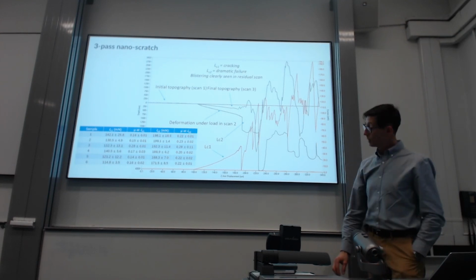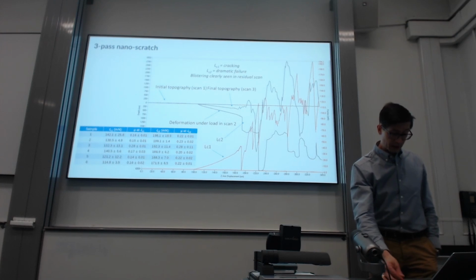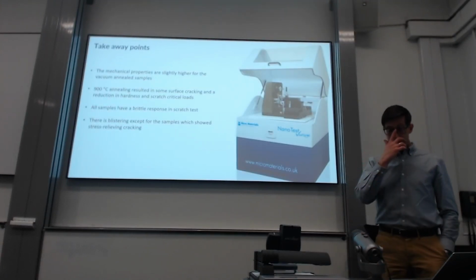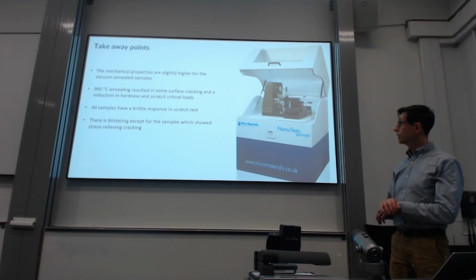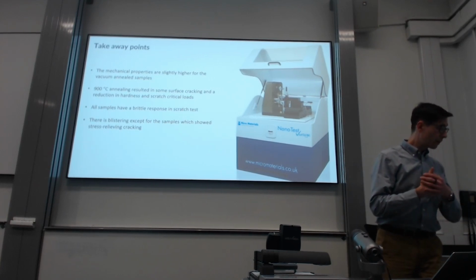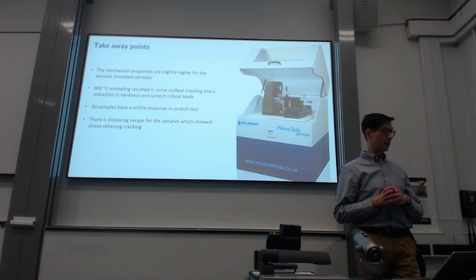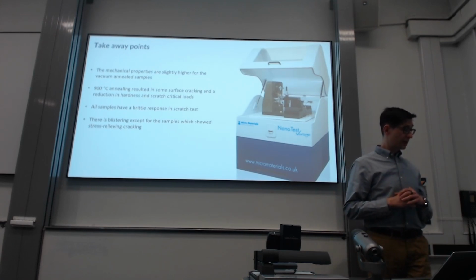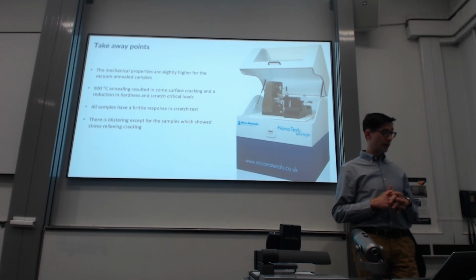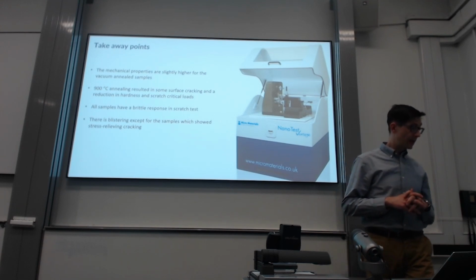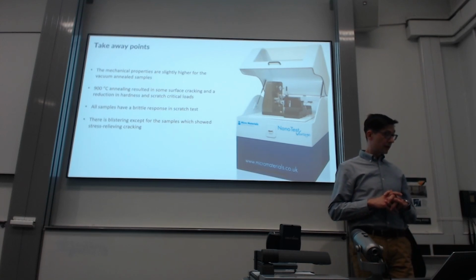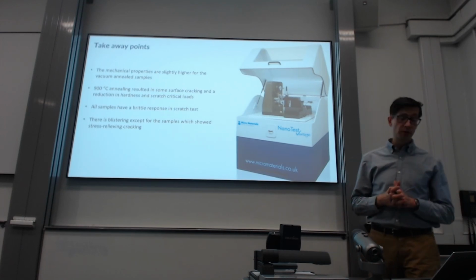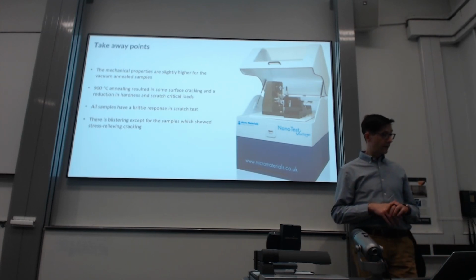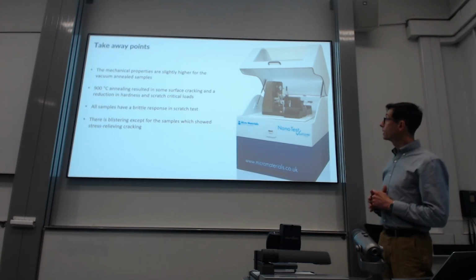I think we need to spend a bit more time looking at some more loads, extracting some more data for those critical events. But in terms of takeaway points from this first part of mechanical characterization, we established that mechanical properties are slightly higher for the vacuum annealed samples. 900 degrees annealing resulted in surface cracking and reduction in hardness and scratch critical loads. Pretty much all samples have shown brittle response in the scratch test, and there is some blistering, except for the samples which showed stress relieving cracking.